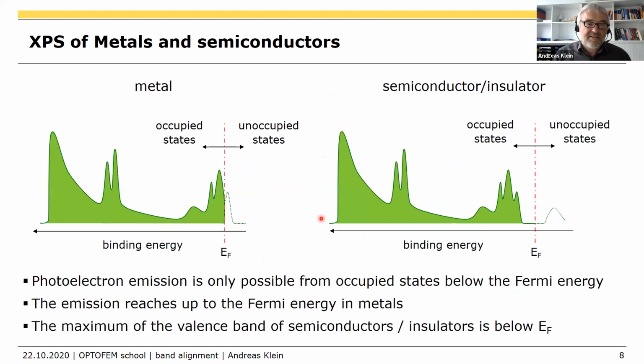Okay, so what's the difference when we do a photoemission of a metal and of a semiconductor? If you have a metal, here are your valence bands, here is a core level, here is the secondary electron edge. This is where the kinetic energy of the electrons is 0. In the metal, the states are occupied until the Fermi energy. Photoemission means we illuminate our sample with X-rays, electrons are emitted. So we can only measure occupied states. So the Fermi level is the highest possible state we can observe in the material.